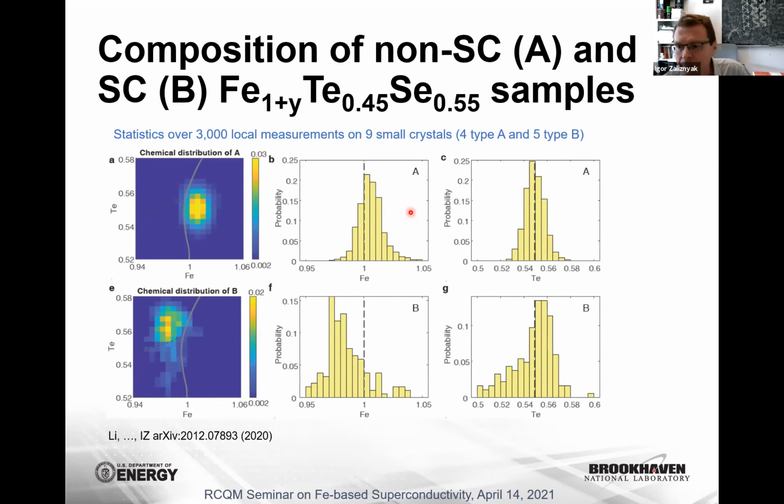The answer is there is so little difference in iron that we don't really know where it is. I see. Do you have a neutron diffuse scattering measurement, maybe on Corelli or something? We have. As I've just said, the amount of extra iron is so small. We have measured the full volume with unpolarized as well as polarized neutrons. Diffuse scattering is totally dominated by magnetic scattering, so there is no structural diffuse scattering that can be associated with structural disorder and imperfections.